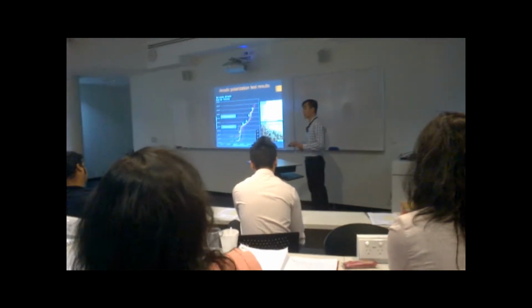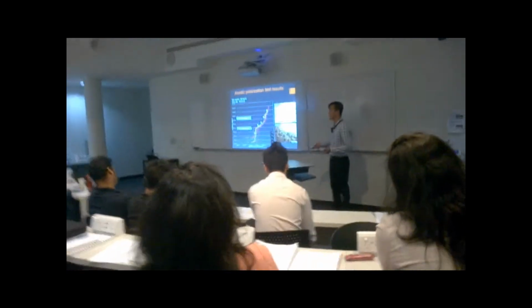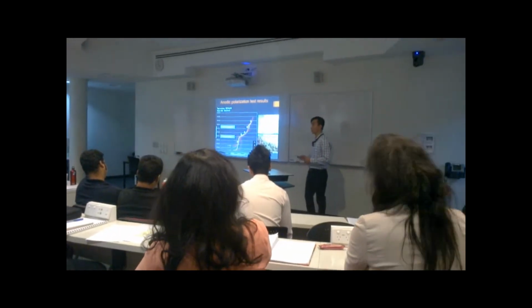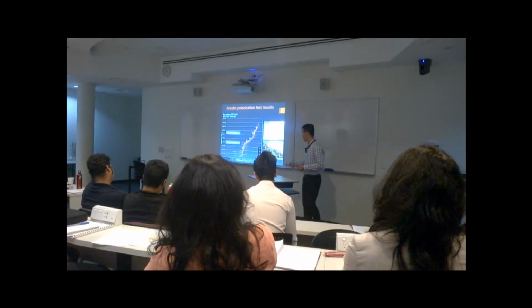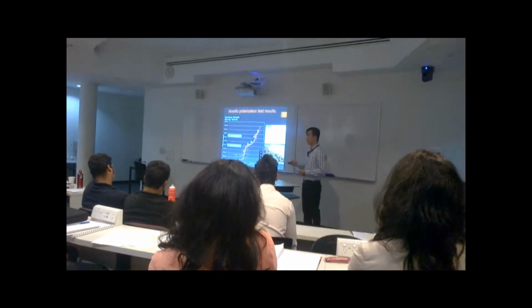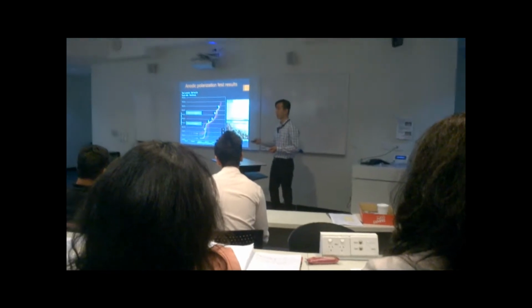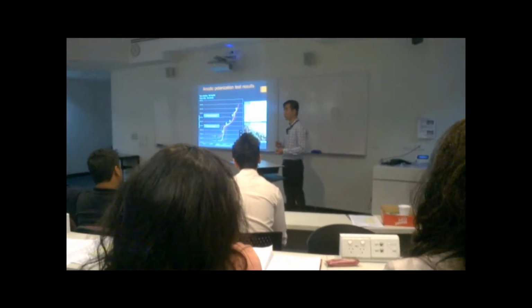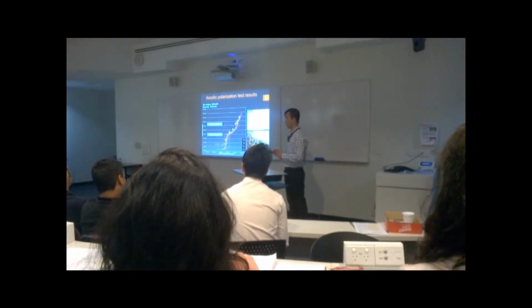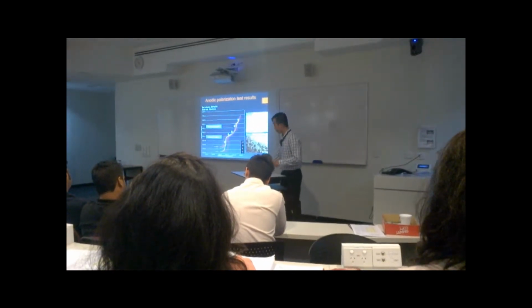And this information was actually very surprising for us, because in the current literature, all the other researchers have found that the carbide is a very stable compound, very corrosion resistant, and usually the matrix starts to corrode before the carbide. And the corrosion of the carbide is, from an engineering point of view, very undesirable, because if the carbide is lost before the matrix, the hardness of the material is reduced, and the wear rate of the part actually accelerates.